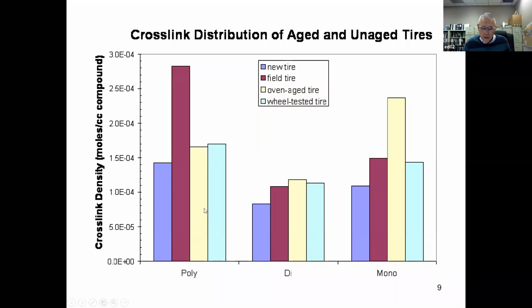and the disulfidics, and then you do a swelling test, and then by subtraction you can calculate the number of crosslinks that are from the polysulfidic type, the disulfidic type, and anything that doesn't get cleaved by the cleavage agent is called the monosulfidic. Okay. So here's the new tire, the number of polysulfidic crosslinks, the number of disulfidic crosslinks, the number of monosulfidic crosslinks. And then the field tire in red, and then the oven aged tire in yellow, and then the wheel aged tire in light blue.